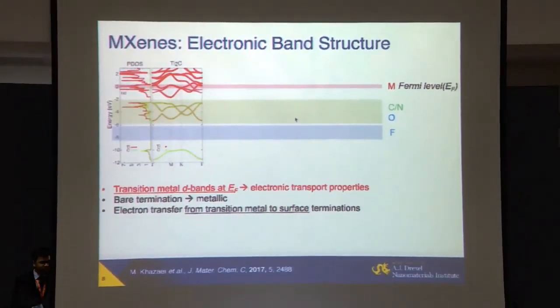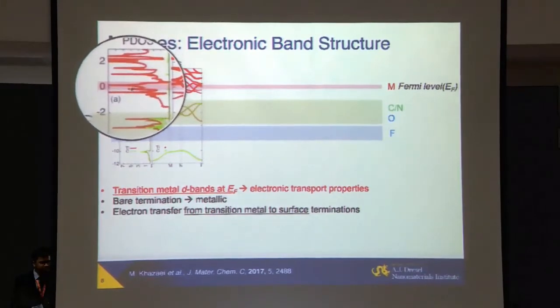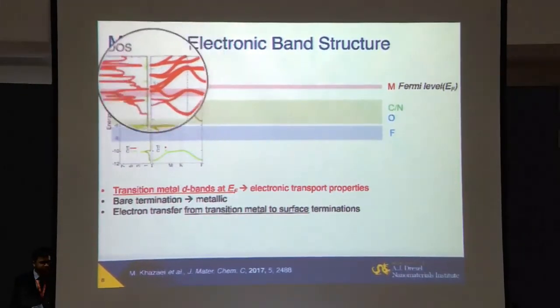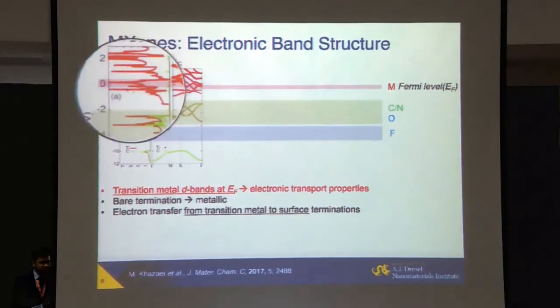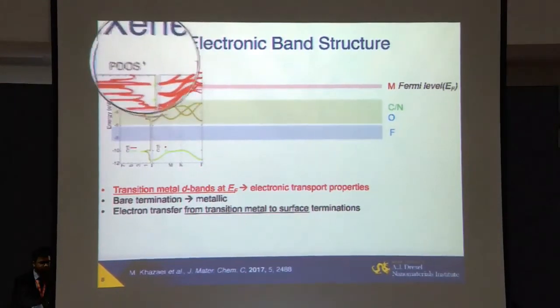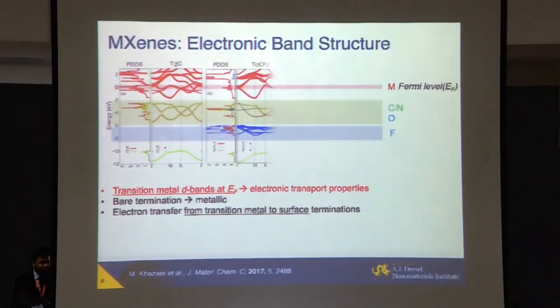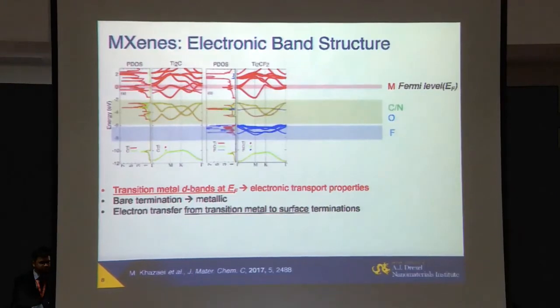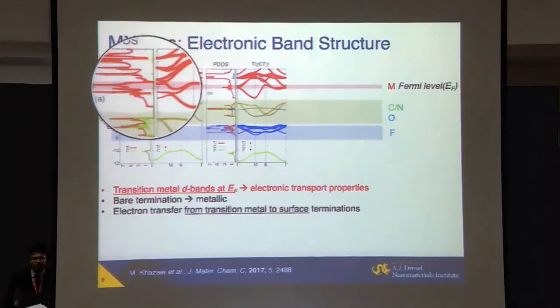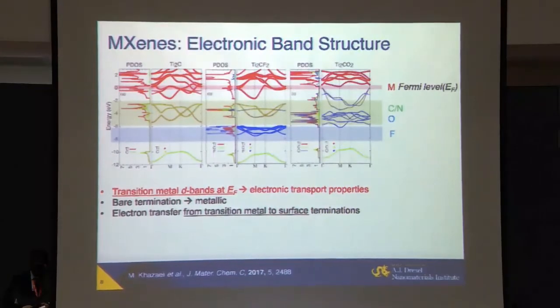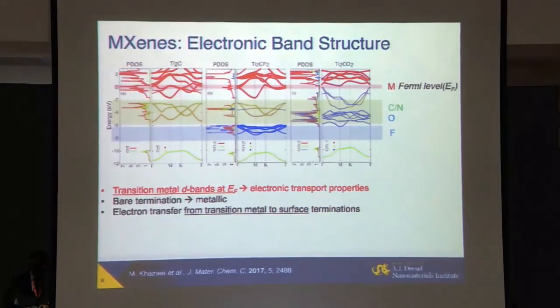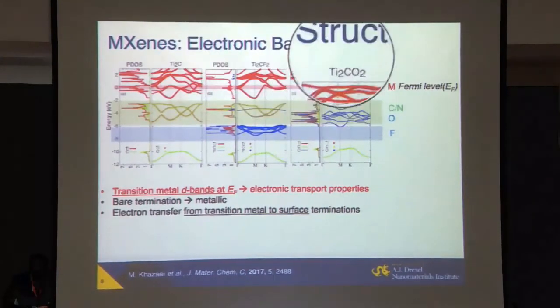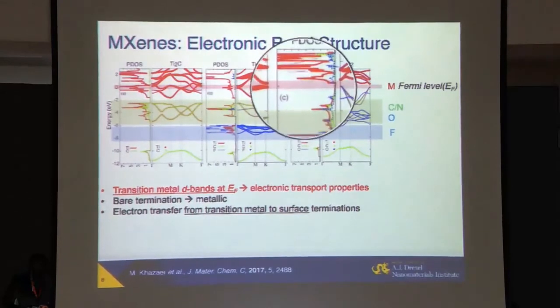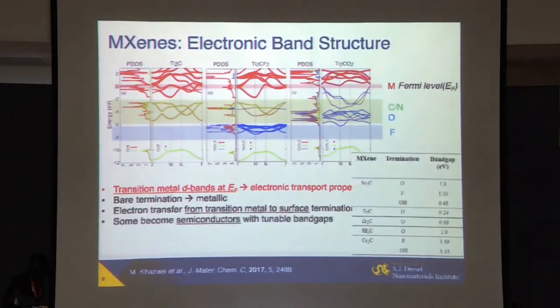But one thing I wanted to mention, which is really important here. If you look at the band structure of, say, this example for titanium 2C, one of the first discovered, actually discovered at the same time, but published a little bit after titanium 3C2. You see there is a high density of states at the Fermi level when the material is non-terminated, sorry, with no surface groups here. If we change the termination, we put fluorine termination on the surface, the density of states, you see, decreases. But if you put oxygen on the surface and pull two electrons from every titanium atom, like in the titanium 2CO2 structure, you can even open the band gap in this material. So this is what I mean by materials with tunable band structure.